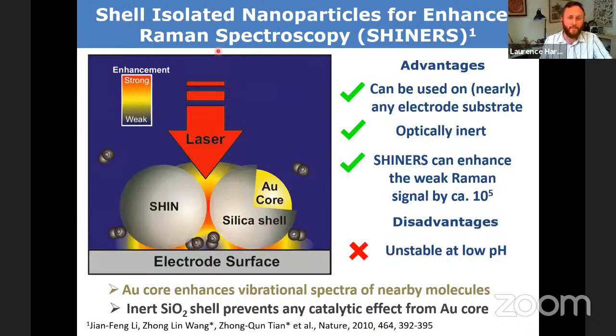And so we have, as I introduced, shell-isolated nanoparticles for enhanced Raman spectroscopy. So now we have our plasmon source, the surface plasmon, locked within a silica shell, our gold nanoparticle. And so we can put our particles onto any electrode surface, and we can enhance the signal of certain components on that surface. So it can be used on pretty much any electrode surface.